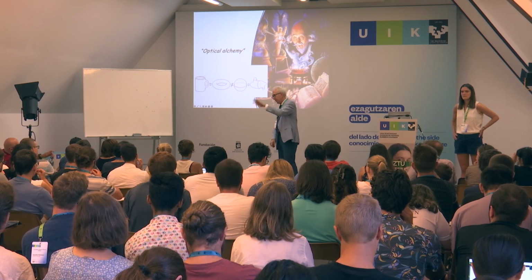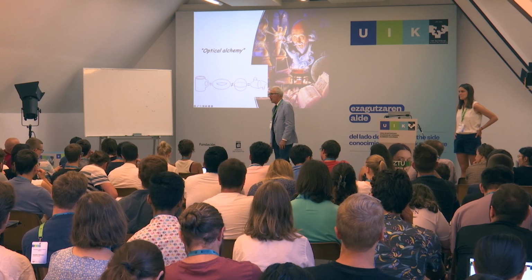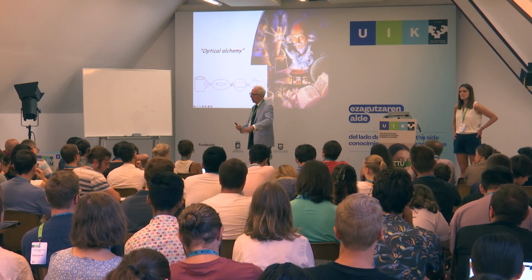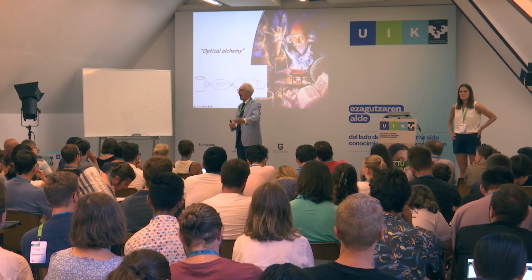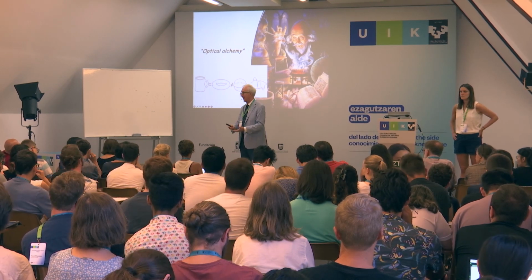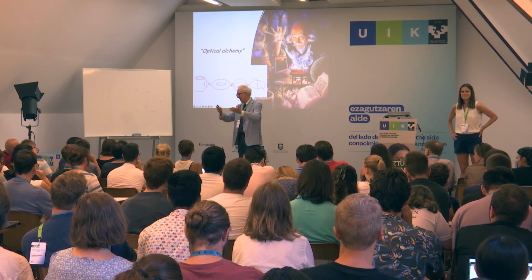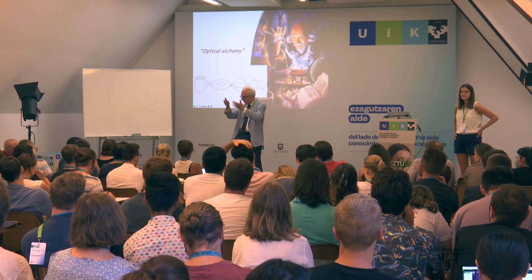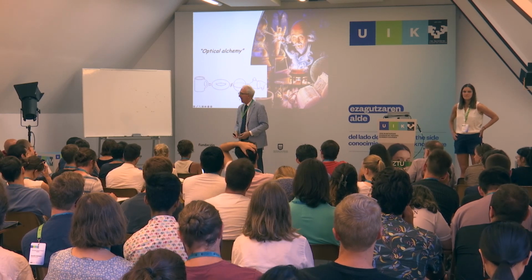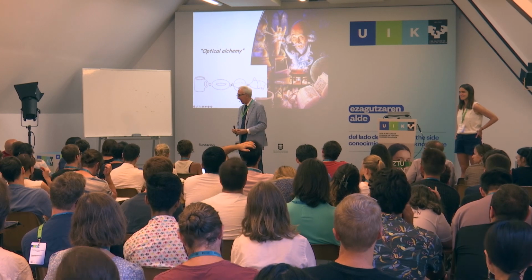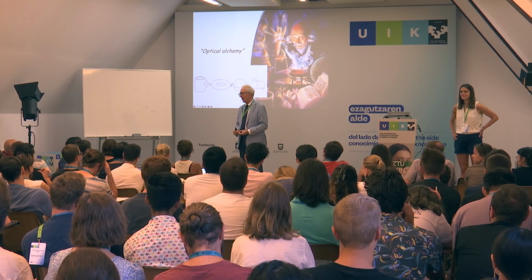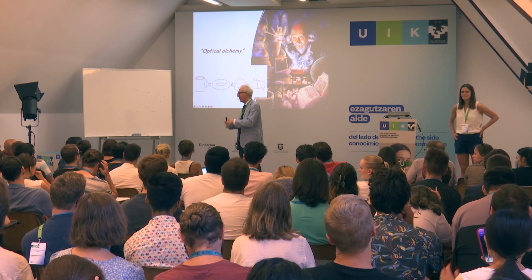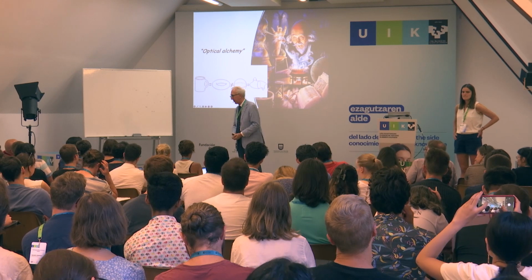That's right. When the pulse polarizes, you cannot do that forever. You cannot move those charges forever. You have to stop. If you put on a CW beam, of course, you can do it for a while, but then you start depleting the valence band, and the carriers are eventually going to recombine and go back down. People have done rough calculations of that, and the result is you'll get a kind of persistent shift current, but it'll be much weaker than the one you just calculate in the perturbation expansion.